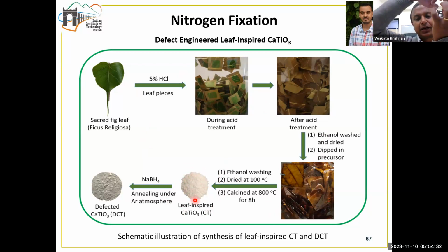And these oxygen vacancy defects make the nitrogen get adsorbed onto them. And because of the high energy, or due to the high charges, these bonds can get broken. The problem with nitrogen is that it has a triple bond, and it requires very high energy to break this nitrogen into multiple things. So if we can successfully do that, that would really do a lot of wonders.